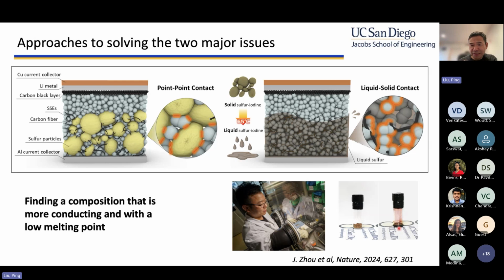And even more interestingly, this red color actually indicates to us the material may be electronically conducting. So if it's electronically conducting, that solves the conductivity problem. If it melts at 65, maybe if our battery degrades, we can reheat it to 65, remelt the material. That will make the interface great. Again, basically, we can heal any interfacial problem due to volume change. And that's precisely what we discovered.